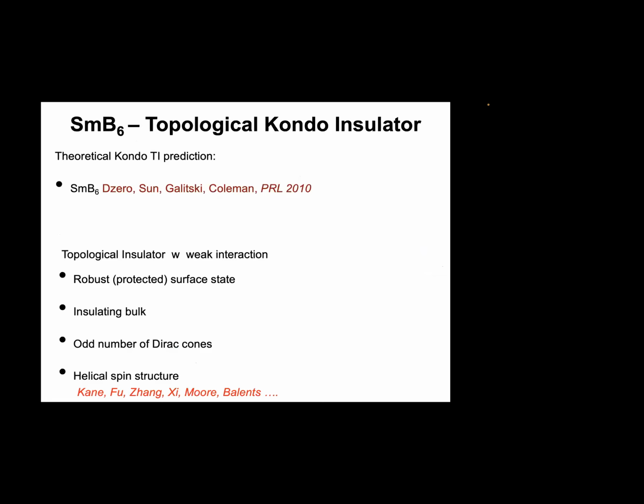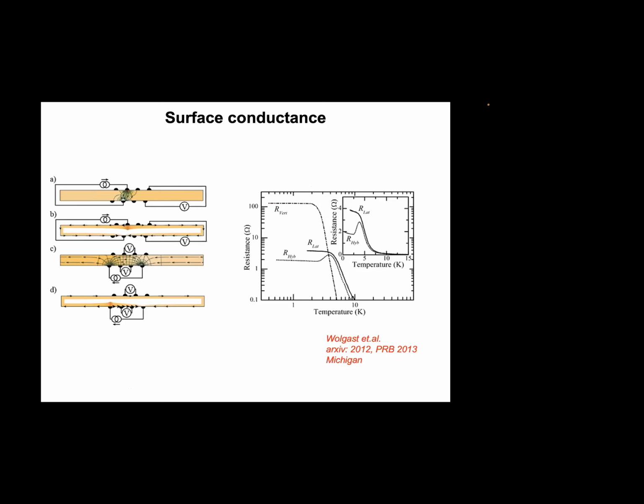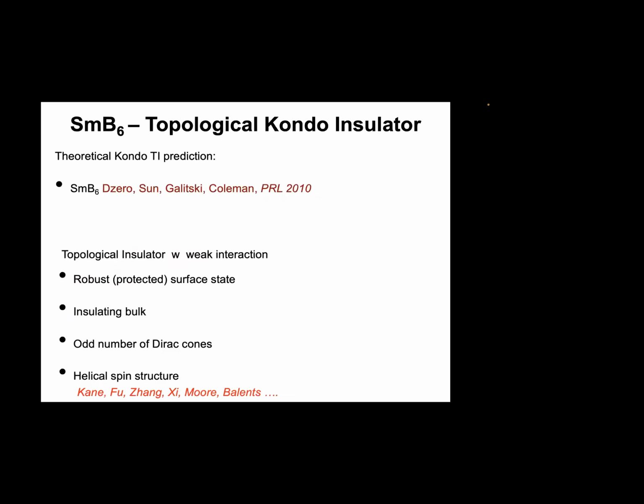As the way of opening a gap, hybridization suggests that there must be a band inversion. In other words, if the general picture that we believe is happening for the bulk gap, there must be band inversion, and that band inversion is just like what happens in the typical topological insulators, bismuth selenide or bismuth telluride. As a result, there will be a topologically protected surface state outside the insulating bulk.